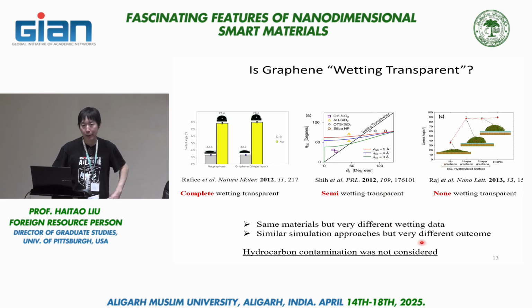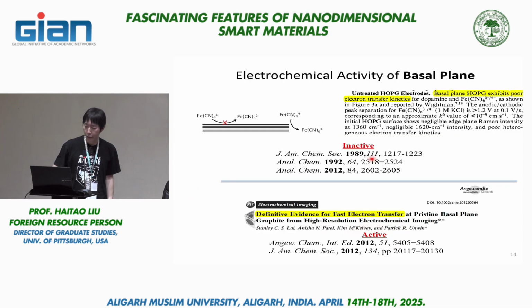But once we look at our data, we realize that they're just looking at the same measurement, but doing it in different ways, and as a result, they are looking at different degrees of surface contamination. And once you take into consideration the surface contamination, we come to the conclusion that the semi-wetting transparency theory is the most appropriate, even though in this case, their wetting data is actually also contaminated by surface hydrocarbon. Okay. So going back to electrochemistry, this is another interesting controversy, and you may notice I like controversies.